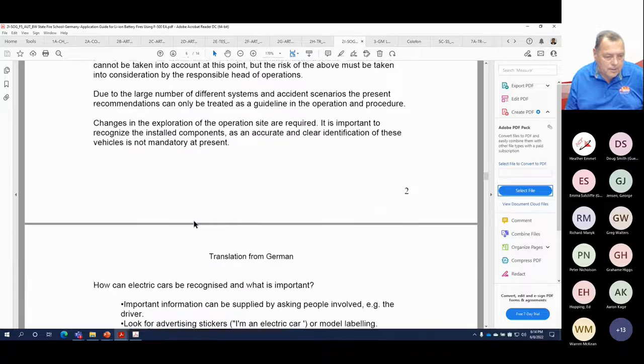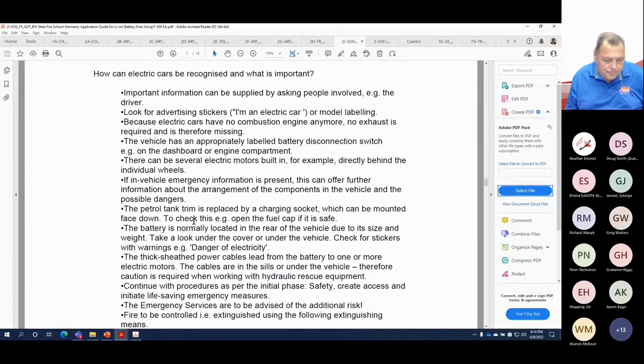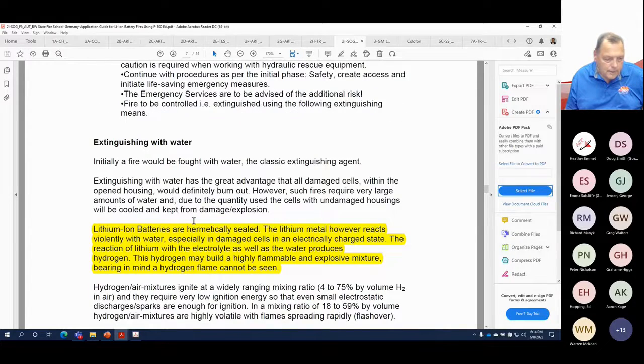Again, I'm going to transmit these reports. Here they talk about batteries and extinguishment with water. Lithium-ion batteries are sealed. The lithium metal, however, reacts violently with water, especially in damaged cells that are in an electrically charged state. The reaction of lithium with the electrolyte as well as water produces hydrogen. This hydrogen can build up highly flammable and explosive mixtures, bearing in mind, hydrogen flames cannot be seen.